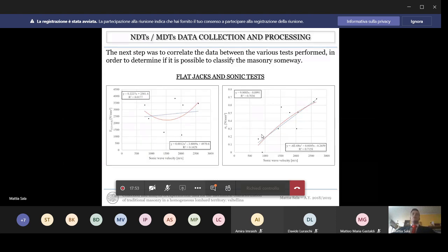So the next step was to try to correlate the various tests performed. The first one is the flat-jacks and sonic test, the deformability modules versus the sonic wave velocity on the left graph. Both in the case of linear and parabolic correlation, there is a scarcity of correlation or relationship. Regarding the graph on the right, the stress state versus the sonic wave velocity, there's a better value with an R-square of 70%, but in any case, this is not a useful result that can be used for the next analysis.